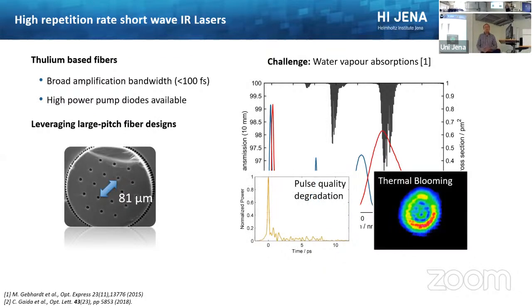And what happens if you propagate a high average power beam through air, just through air, can be seen here. You degrade your pulse in time, and you have what we call thermal blooming. So your nice beam gets into this kind of ring structure due to absorption in air, which increases the temperature in air, and this leads to basic thermal lensing, just by propagating through air. So if you want to operate these systems, you need to use a quite dry atmosphere or even vacuum.